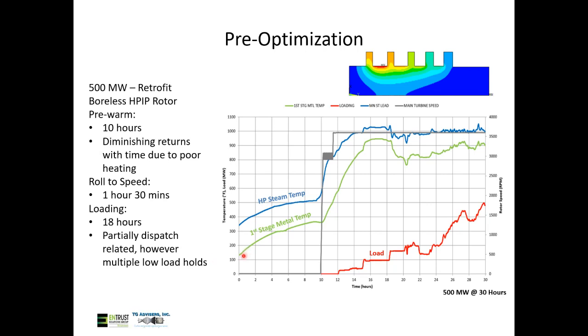In this case, they had to get to 350 degrees first stage HP metal temperature, and it took roughly 10 hours of this steam pulsing to get there. When you look at it, if I cut off this final 4 hours, the difference is only 50 degrees of benefit. So you get diminishing returns with time. If we were to roll up to a low speed hold, we would get better heat transfer, a little better flow, and quicker heating. So there are ways to modify that and cut back on the time without compromising the safety of the unit.